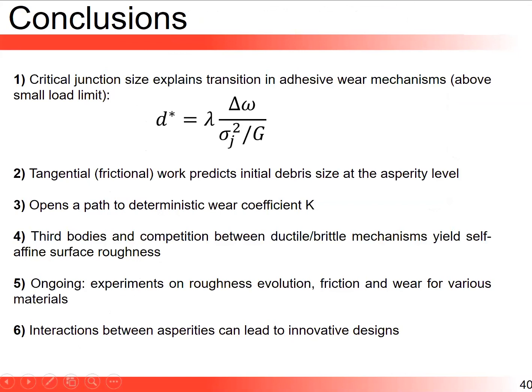So with this, I am at the end of my talk. Let me remind you of some of the key points. I mentioned the fact that you have a critical junction size that explains the transition in adhesive wear mechanism, a function of material properties. I told you that the tangential frictional work predicts, without fit parameters, the initial debris size at the asperity level. This opens a path to a deterministic wear coefficient K, because K is not a probability, it's deterministic for us. I've shown you also that third bodies and competition between ductile and brittle mechanisms yield self-affine surface roughness that naturally comes out of our model.